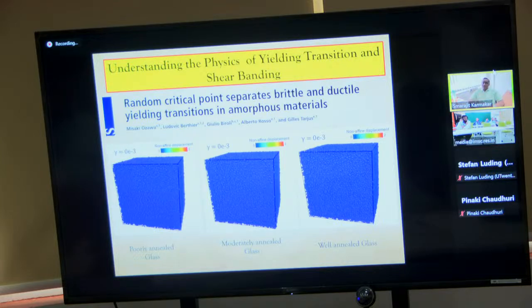And in similar studies done in 2 dimensions, the speed up was around 10 to the 10, which is enormous. And it has been claimed that one can reach glassy states which even with experiment would be nearly impossible. So now with these advances, we are in a phase where a simulated glass can be compared easily and directly with an experimental glass, at least.